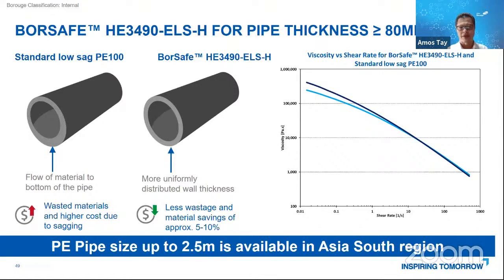So if you look at the chart on the right side, this is just a viscosity versus shear chart. The dark one is the ELSH, and then the lighter color is the standard PE100. When you see that it's nearer to the y-axis, it means the material exits the die, so there's zero shear. When the material comes out from the die, typically when molten, it will flow with gravity and go downwards. But the darker color shows that it has a higher resistance to flow, so the material can stay in a good shape around the circumference.